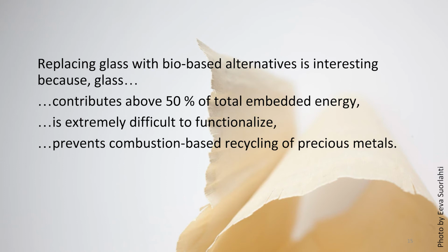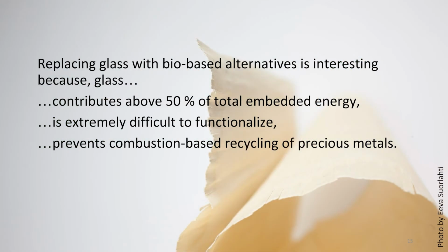The motivation for utilizing cellulose substrates or wood-based substrates comes from the fact that glass contributes over 50% of the total embedded energy in solar cells, in these emerging solar cell types. So if we want to reduce the energy payback time of these devices, we should look at alternative substrate materials. The other fact is that glass is also extremely difficult to functionalize to get additional optical functions. This is because glass is prepared at high temperatures, and many advanced functional materials wouldn't survive the preparation process of the glass. Whereas cellulose is very good for all kinds of functionalization.